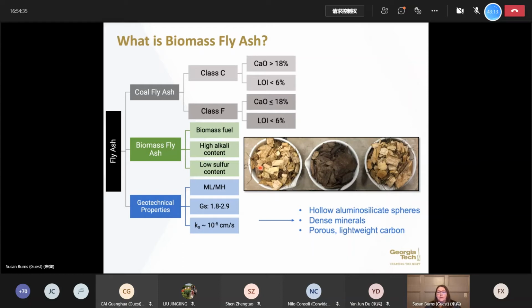In both cases, what we'll see is that the geotechnical properties can be very similar. So in general, this is a silty material. It can be low or high plasticity. Specific gravity will range from a little bit less than 2 up to as high as 3. On the low end, we have a high organic content. On the higher end, our iron oxides tend to increase. And generally what we'll see is that it has a saturated conductivity, as we would expect, as a function of particle size on the order of about 10 to the -5 centimeters per second.